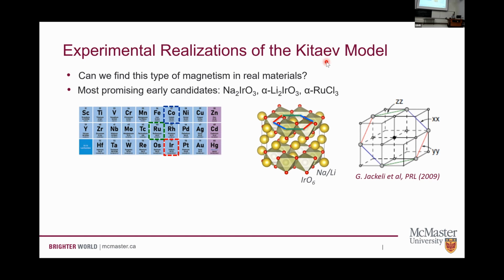Some of the first materials that were suggested as candidates for this Kitaev model physics were all honeycomb lattice materials, either based on iridium or based on ruthenium. Iridium, again, is down here in 5D, with the strongest spin orbit coupling and quantum spins, which is good news. If you go up to ruthenium, the spin orbit coupling is a little weaker. Remember, it scales like the atomic number to the 4th power. But for the right geometry, the other energy scales can scale as well, and maybe we have a chance. More recently, there have been some arguments that you can find Kitaev physics even up here in some of these 3D materials if you design them correctly. So you'll also see some new papers talking about cobalt Kitaev systems. We're going to focus down here for today.